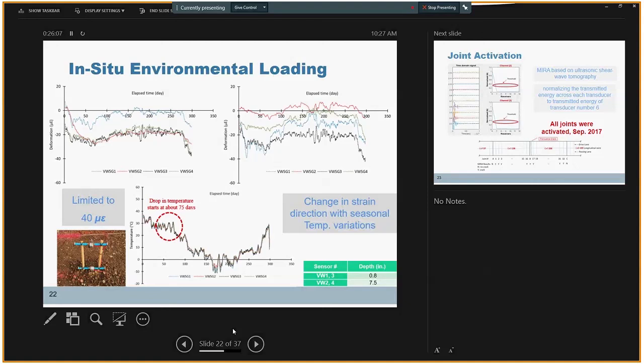And overall, the in situ strain values were limited to about 40 microstrain over the first year. And I should note that the numbers we have here are a combination of the effect of environmental conditions, variation in temperature, relative humidity, curling and warping of the pavement, and also shrinkage of the material itself. Overall, we had comparable numbers, comparable total deformations and maximum deformations for these two concrete types, regardless of the binder content.